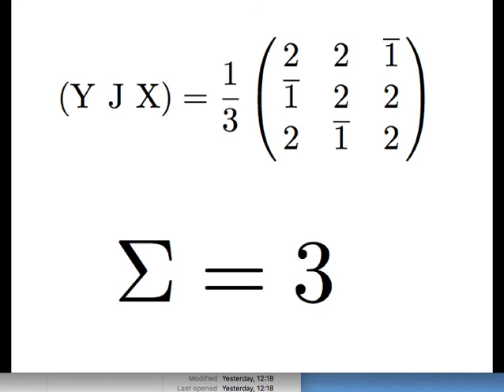Simply because the coincidence site lattice vector must have integers. So it's very easy, just by looking at the rotation matrix, to get the sigma value. On your scanning electron microscope, where we do electron backscattered diffraction, you can often ask it to give you the sigma values between two adjacent crystals. All it does is work out the rotation matrix, find the common factor, and give you a sigma value. And bear in mind that as we go to larger and larger sigma values, they are not really important, because the fraction of coincidence points which are common will be too small to have a significant effect on the boundary.